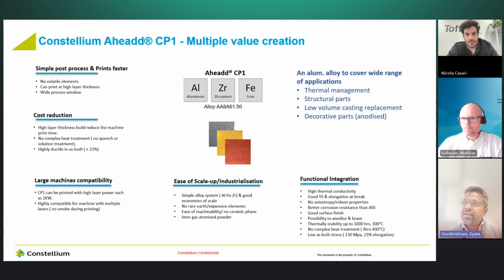So in a nutshell, when we look at CP1, it's not only helping you to build structural or thermal components. You can combine applications, or you can create components integrated with functionality. If you look at the composition, it's a simple composition: aluminum, zirconium, and iron. There is no rare earth, no expensive material, so the material is not that expensive. And as there are no volatile elements, you are able to print the material very fast if your printer is equipped with higher power, such as 700 watt or 1 kilowatt. That brings your component cost down because you are able to print fast.